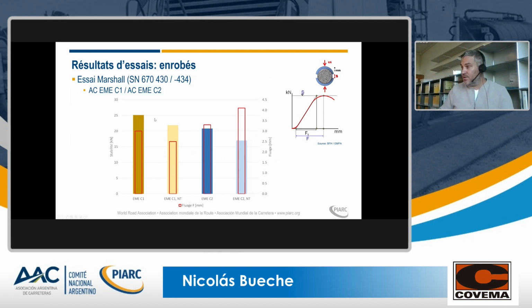And here you could see, for instance, if you just consider the Marshall stability, it was higher with the hot mix asphalt than for the warm mix, and this for both the C1 and the C2. And this was, let's say, quite interesting. Even this is something that we could expect, once again, based on aging aspects.